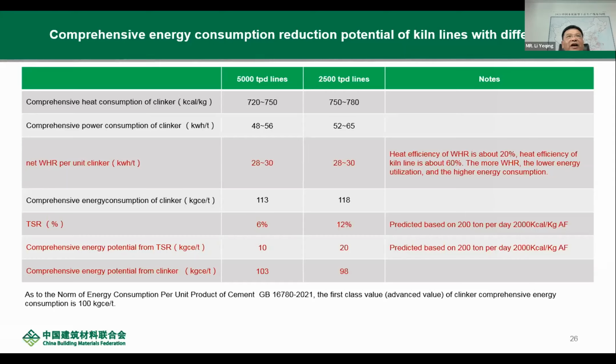Another is 2,500 tons. The calculation is based on the fuel program and the energy consumption. The 5,000 is low for sure. However, if we use some of the same weight of alternative fuel, the AF ratio of the small capacity line is high, because the same AF amount can satisfy the smaller capacity line better compared with the biggest capacity line. Finally, the energy consumption is similar. The line with the smaller capacity can be reduced much more easily. This is the result we get from the scientific calculation.